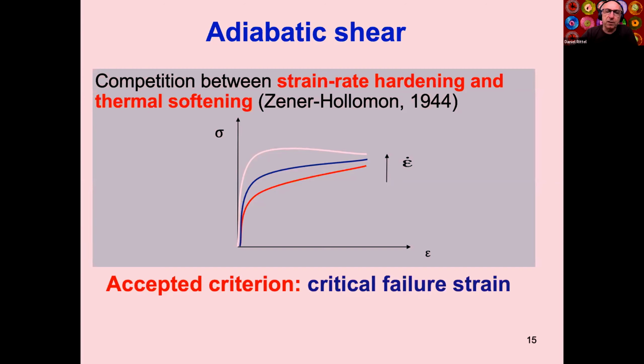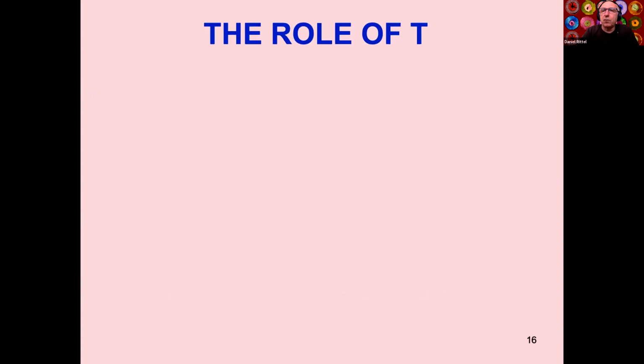So the accepted criterion, because this is an instability, and you still need a criterion when you do calculations, and you would like to define a failure criterion for your calculations, is that of a failure strain. So people put a failure strain, and they believe that at a certain strain, the material will localize. And that's okay for me. So let's start with the role of temperature, because temperature is the prime suspect. As the strain rate increases, the heat generation increases, the temperature rises because of adiabatic conditions, and therefore material softening occurs, which leads to loss of stability.